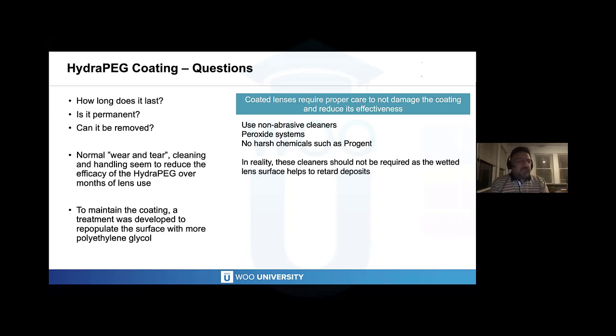So some of the questions that people ask is, well, how long does this coating last? Does it come off? Is it permanent? Can it be removed? And the reality is that it is a permanent bond, but with normal wear and tear, handling of the lens, rubbing the lens across contact lens cases, things like that, it does seem to reduce the efficacy of the HydraPeg over months and months of use. We do seem to see that over time, patients would report maybe the initial benefit slowly deteriorates over months and months of use. And so there's now a product available to do an in-home surface retreatment or recoating or repopulation, if you will, of that PEG-based polymer so that patients can maintain the full effective coating over the lifetime of their lens rather than having it slowly erode over months of wear.